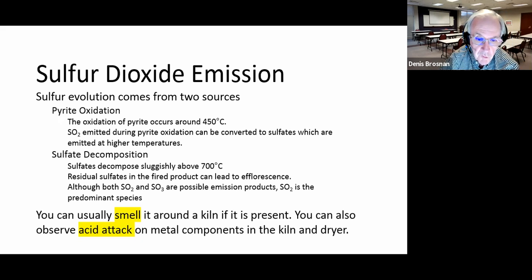So it comes from two places: pyrite oxidation. Iron sulfide is pyrite, which is entrained in a lot of natural clays. If these clays come from areas where iron was mined, I find more pyrite in clays from these areas, and so you're going to have the oxidation of pyrite at about 450 degrees C. It's a fairly complex oxidation, and of course, people that make heavy clay products know that they want to get all the pyrite oxidized during firing, otherwise they're going to have some discoloration potential with the product and service. Sulfur dioxide can also come from decomposition of sulfates. Usually sulfates are really undesirable in ceramic products as a presence.